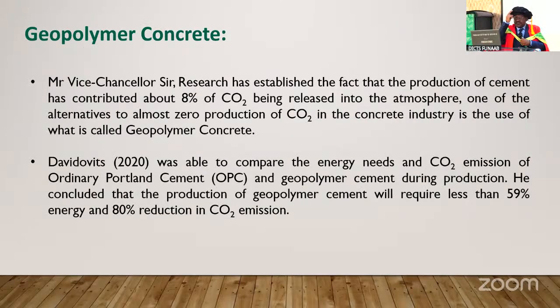Geopolymer concrete. Mr. Vice Chancellor, sir, research has established the fact that the production of cement contributes about 8% of carbon dioxide emission released to the atmosphere. One of the alternatives for almost zero production of CO2 in the concrete industry is the use of what is called geopolymer concrete. Davidovits in 2020 was able to compare the energy needs and the carbon dioxide emission of ordinary Portland cement and geopolymer cement during production. He concluded that the production of geopolymer cement will require 59% less energy and 80% reduction in CO2 emission.